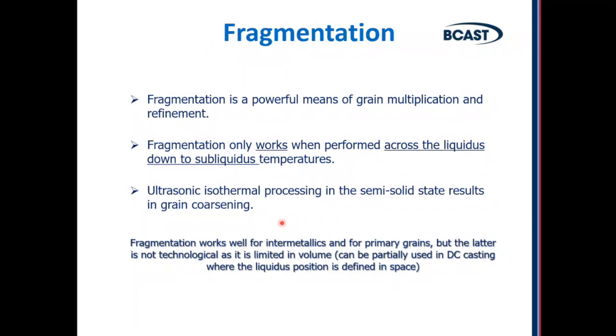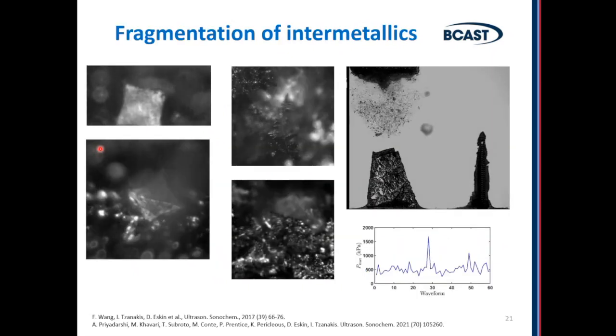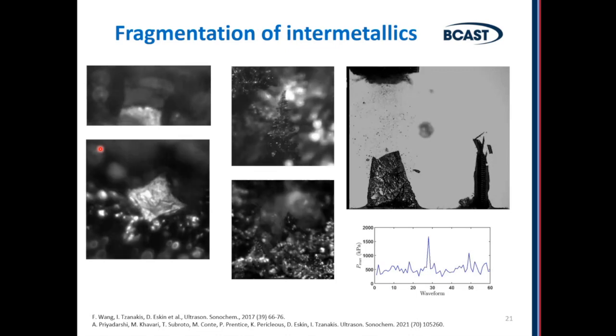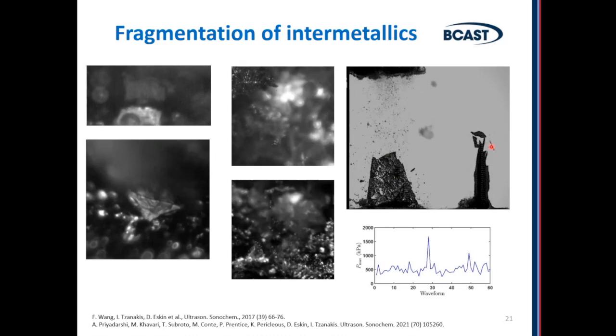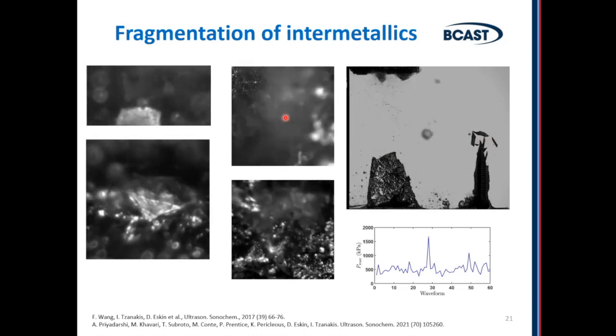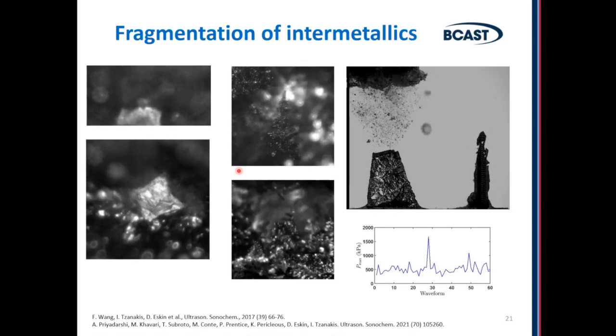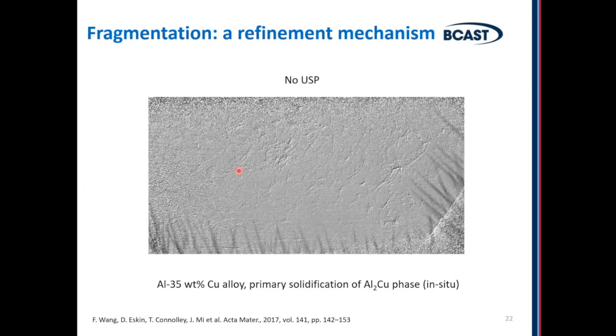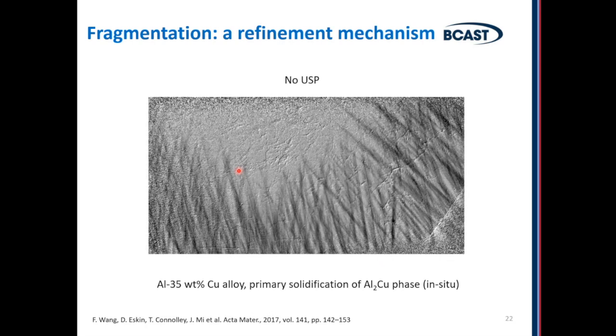Fragmentation is another powerful means of grain multiplication, grain refinement. It works always, but it only works when you do it below the liquidus, because in order to fragment something, you need to have it. So if you talk about fragmentation of aluminium dendrites, for example, or intermetallics, you need to do it in the temperature range where this solid phase already exists. And it works very well. We had a lot of in situ observations of how cavitation can fragment intermetallics. You can see here and here. Basically it crushes them, the only interesting thing is that it is not happening instantaneously. Actually, it's a kind of fatigue mechanism, a high frequency fatigue mechanism.